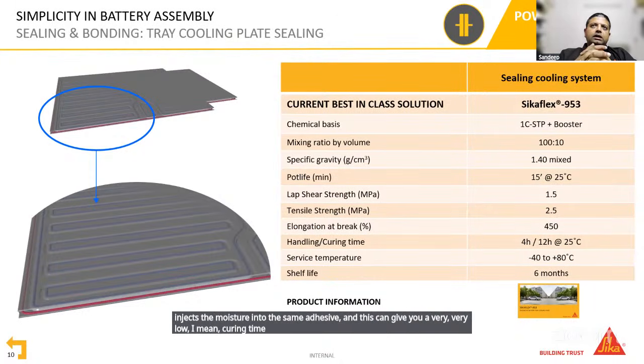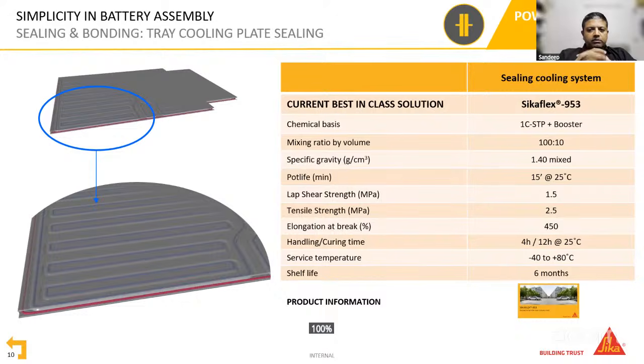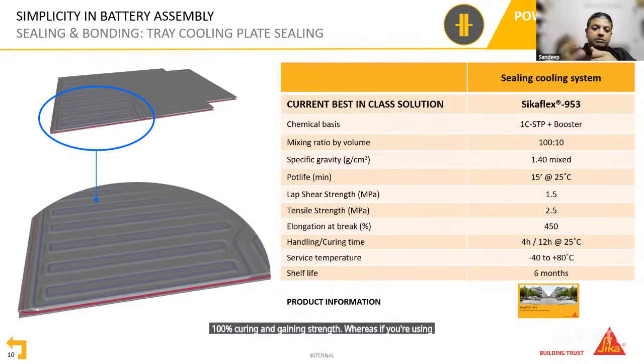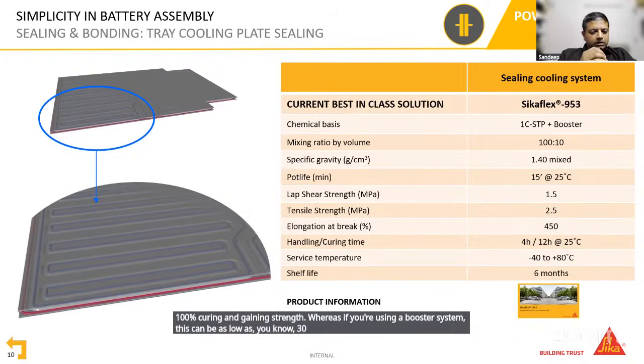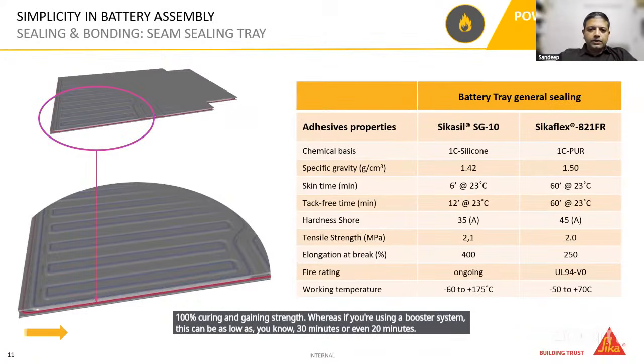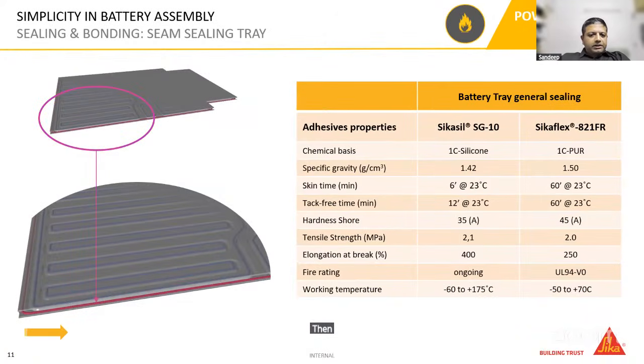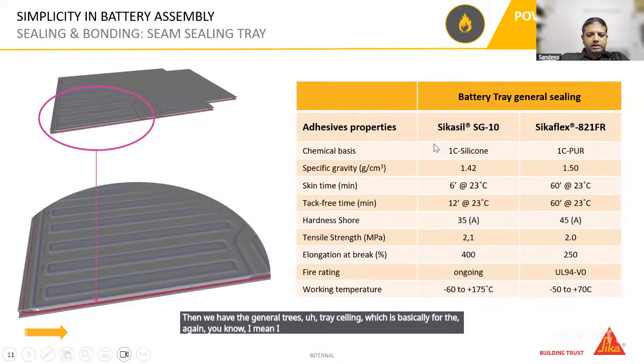So typically, a standard adhesive can take anywhere between 4 hours to 24 hours for 100% curing and gaining strength. Whereas if you're using a booster system, this can be as low as 30 minutes or even 20 minutes. Then we have the general tray sealing, which is basically for the IP 67, 68 rating. This is not used for the coolant application, but for the general tray sealing where it is not in direct contact with any kind of fluids.